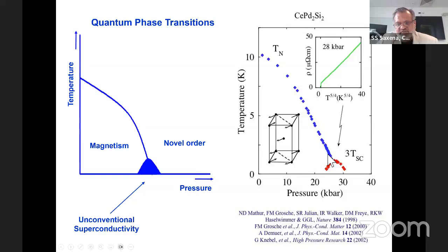And then we have, at least since 1998, if not before, because these ideas were explored even earlier, what we call a non-Fermi liquid state, where you break this canonical state because you create fluctuations, magnetic fluctuations in this case. When you're suppressing magnetism down towards zero, it starts to fluctuate. So in your mind, you can build a picture: the electrons are scattering from these magnetic fluctuations, and that's what gives you these different power laws.